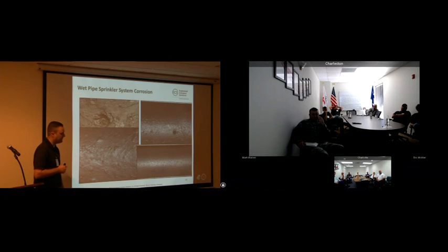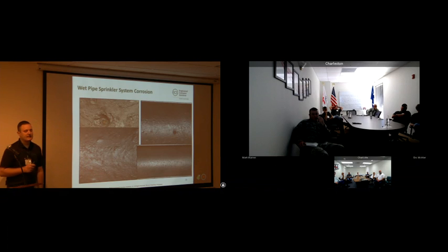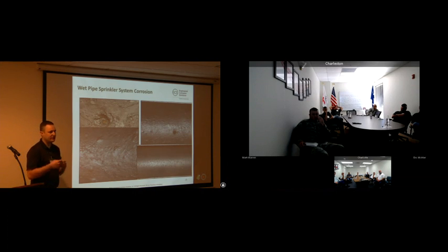That's characteristic of acid corrosion. Where we find that sometimes is in a dry system when we have a compressor putting in moisture. So you compress air, you heat it up, it can hold more moisture. It goes into the system, it cools off, it releases that moisture. That moisture is then distilled water. Distilled water means it has no dissolved mineral content, it has no ability to buffer its pH.